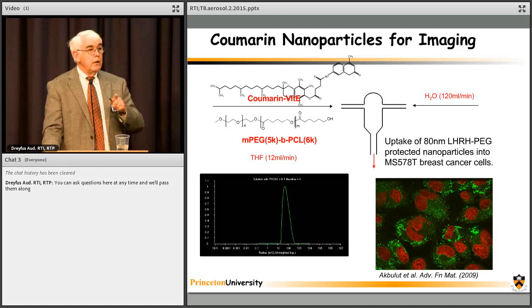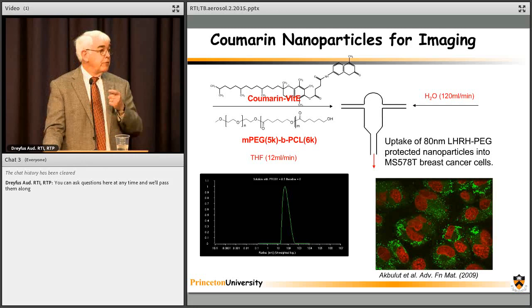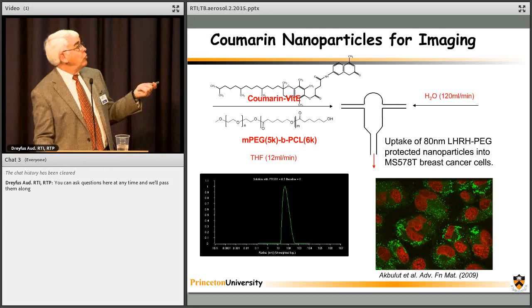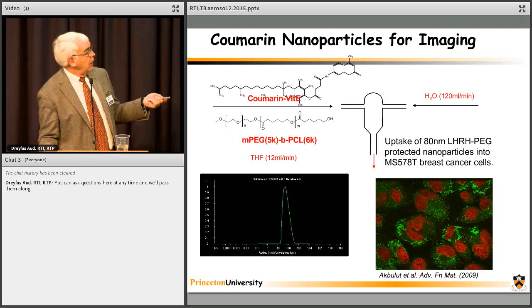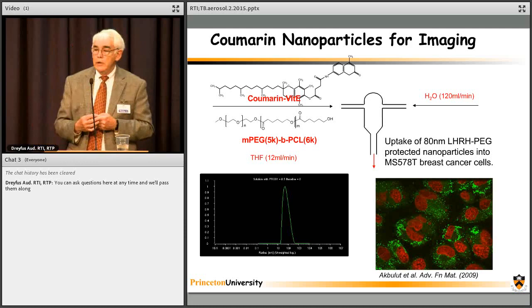We want it to be in the core, so we want a very hydrophobic material. So it stays in the core, and therefore we can follow the fate of the nanoparticle, not something that partitions out. You can take something like coumarin, which is water soluble, and link it to vitamin E, and you can make these 100 nanometer particles. And this is an LHRH targeted, a peptide targeted nanoparticle going into a breast cancer cell line. The green are our nanoparticles, so they've been internalized into these breast cancer cells and endosomes in the cells and are then released.